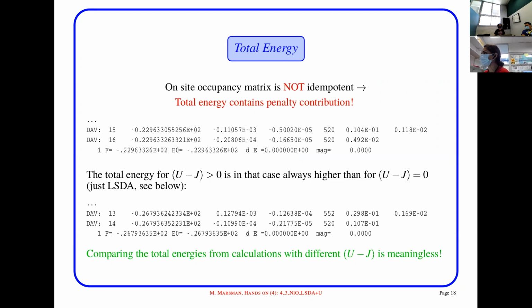In the group where we needed to use the U, for instance in my project about the copper oxide, what we did is to calculate the same system with U and without U and show that some parameters were independent. Because if you manage to show that with the U or without the U the result is the same, then you are done, because people cannot say, but why use the U?